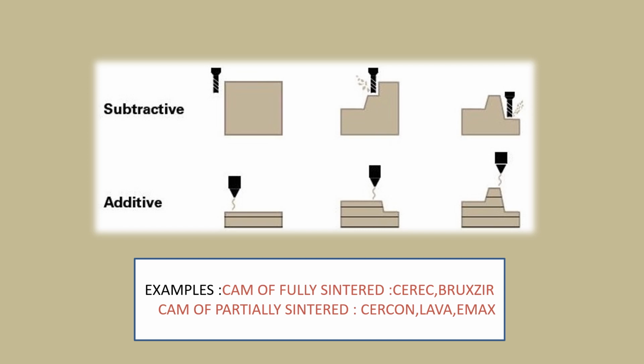In additive technology, the crown is made by adding up the porcelain powder particles layer by layer successively. For each layer of material, the powder material and liquid material are added and fused successively to form the final shape. Whereas coming to the subtractive approach, it is usually accomplished by computerized milling devices which are numerically controlled. This is something similar to carving, wherein you are going to eliminate the excess material, resulting in the formation of your final shape. Coming to the examples, fully sintered are Cerec and Bruxzir, whereas partially sintered are Cercon, Lava and Emax.